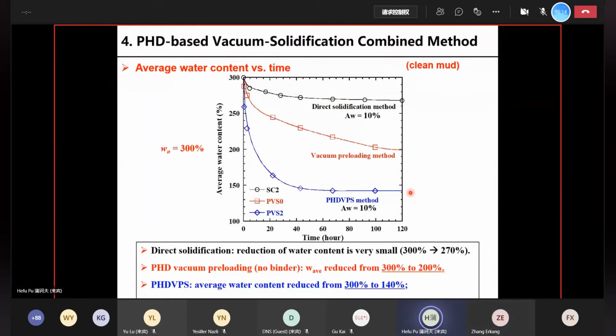And most interesting is the PHDVPS method. In this case, the average water content reduced even more significantly from 300% to 140%.